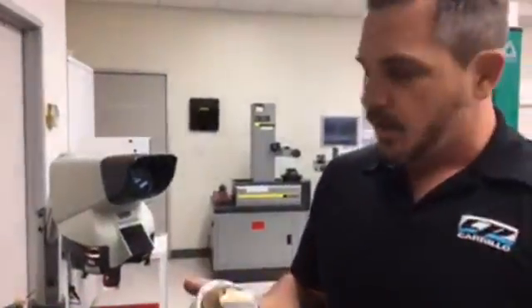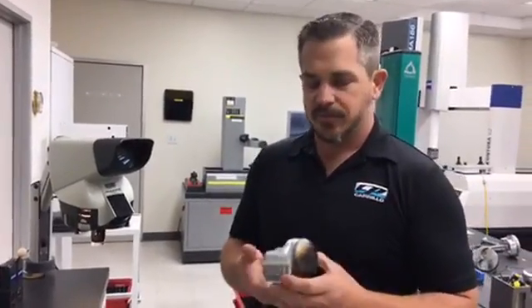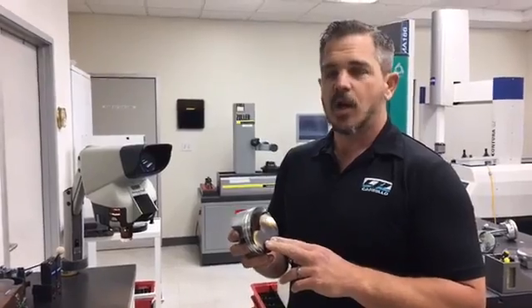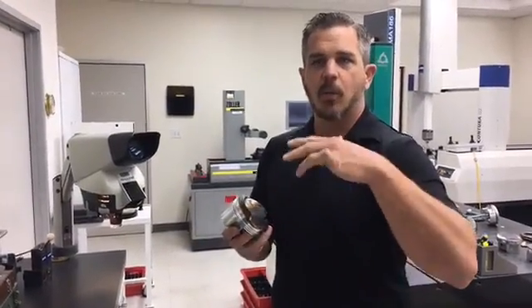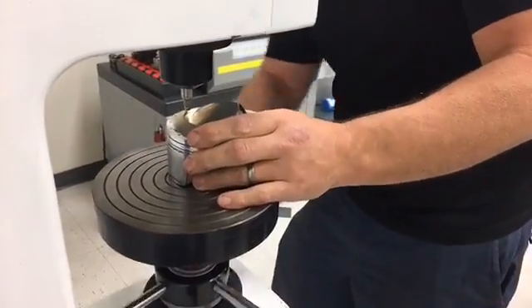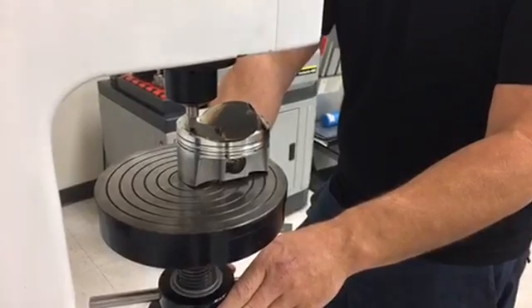This is a piston out of a sprint car. What we want to look at next is the running condition or tune-up of the engine — it's something most engine shops don't have but is probably the most valuable tool for inspecting your piston after a season: Rockwell testing the part. A lot of times you can visually look at a piston and think it looks great, but it could be super soft. These pistons start off forged between 76 and 78 Rockwell, and as they get more time or abuse, or if the tune-up is wrong and they run lean, it starts to cook the part and you'll see the Rockwell go down substantially. We take it over to the Rockwell tester and check the deck and the spark plug side.